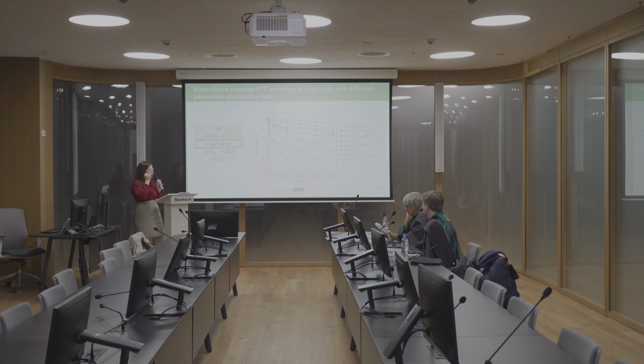So, and if we talk about finding the better composition for improving the degradation, in this work we, just to save time and save our resources, mostly used materials that were already in literature, and they were confirmed to have quite good results regarding the efficiency, regarding their structure, phase purity, and regarding their stability. But in most of the cases, they were investigated for photo-induced degradation, and we decided to check them also in case for electrochemical degradation.